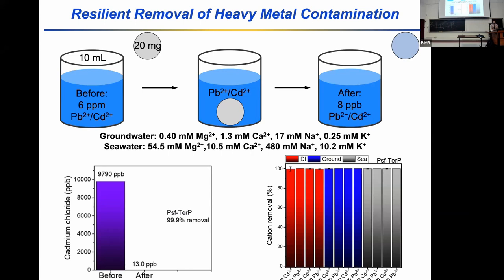And most excitingly to me is that this persists in deionized water, which you see in the red bars, in a simulated groundwater, which you see in the blue bars, or a synthetic seawater, which you see as these bars. And the synthetic seawater has about 35,000 parts per million competing or interfering electrolytes trying to find those binding sites as well.